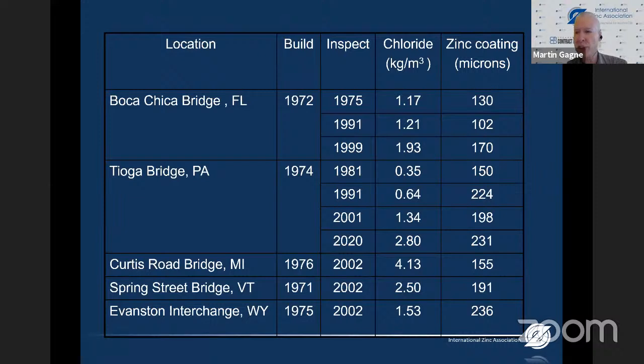The International Zinc Association has been following a number of bridges. We take core samples, so we drill a hole, we pull out the core, we look at the chloride loading in the concrete next to the reinforcing steel, and then we measure the remaining zinc thickness on the reinforcing steel. So we can see here for a number of bridges that are approaching 50 years old, the chloride loadings are quite high. We can see in one case, the Curtis Road Bridge, this is almost 7 times the chloride loading for black steel, but the zinc coating is still in good condition.